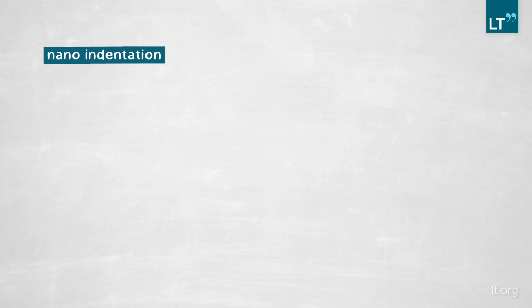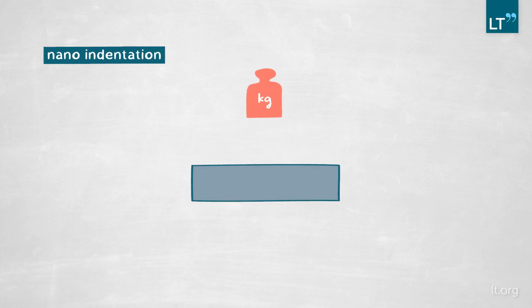We take a very sharp indenter tip of a few hundred nanometers and we push it inside of a material. At the same time, we track the force that we use during this process and we measure the distance that it penetrates. This allows us to get information, for example, on how hard a material is, how easy or difficult it is to deform it, or if there are cracks evolving.